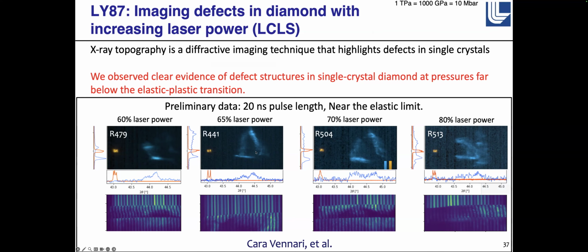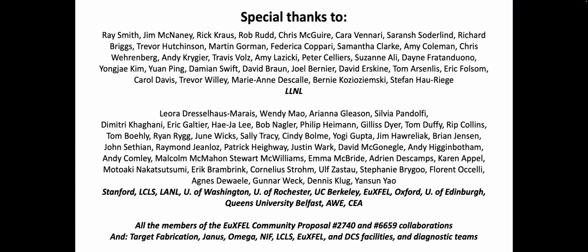And when we drove it up to roughly the elastic limit, we saw very, very big diffraction. So we no longer saw the single crystal. We're trying to figure out what is causing this. I think that we're forming a lot of defects even within the elastic regime, which is exciting to be able to look at.